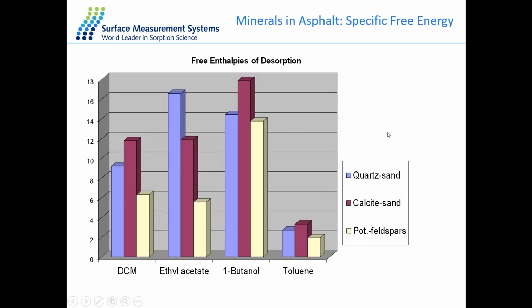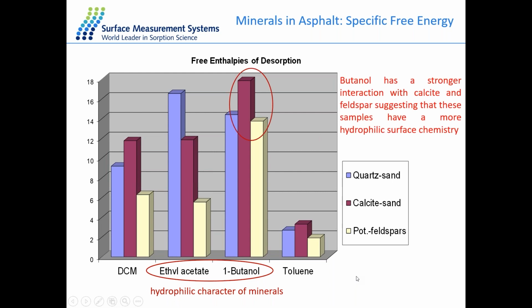We also calculated the specific free energy, like I mentioned, with the following molecules below. First of all, we can understand that each material has different affinities and different interactions with each of these polar probes. What's interesting is that all three of them have a very low interaction with toluene. However, the differences are more prominent with ethyl acetate and butanol. Looking at butanol, we can see that the calcite sand material has the strongest affinity with butanol. This suggests that this sample has a more hydrophilic surface chemistry, and it has more hydrogen bonds available to interact with our butanol.